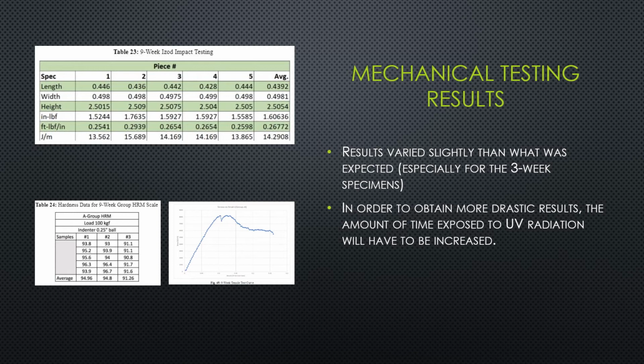As for the 6 and 9 week batches, we started to see what we thought would happen, the degradation of the part. This gave us slight results from our control, nothing very much statistically to go off of as far as significance. In order to get a more drastic result as far as degradation, these parts would have to be in our UV curable box for a longer period of time than just the 9 weeks that we maxed out these specimens at.